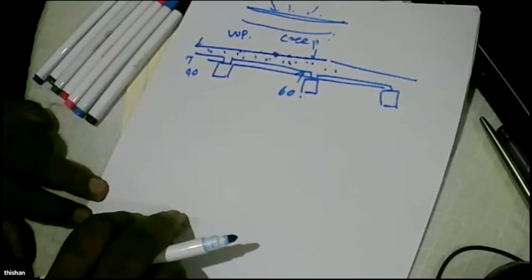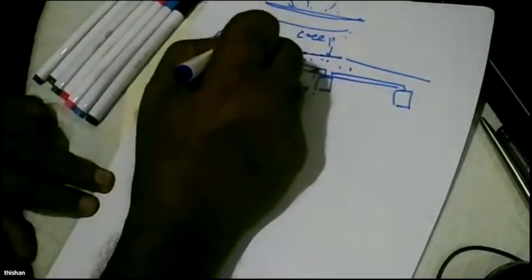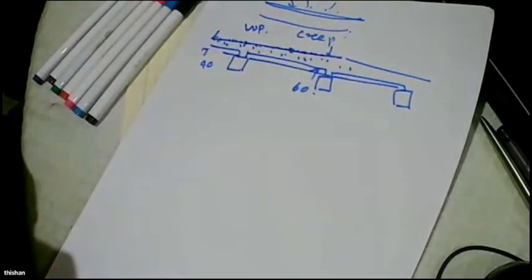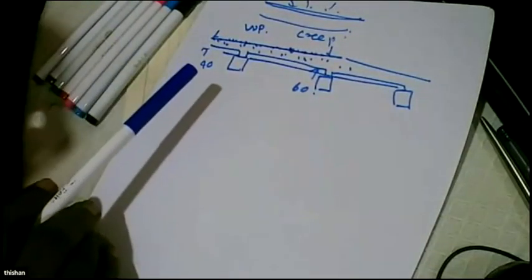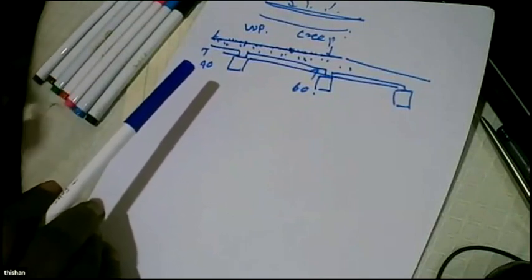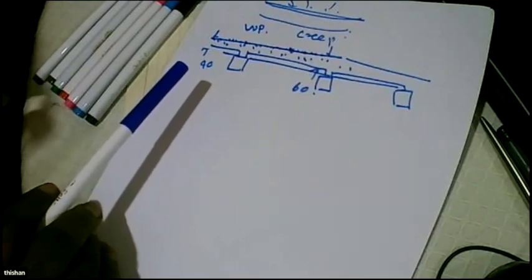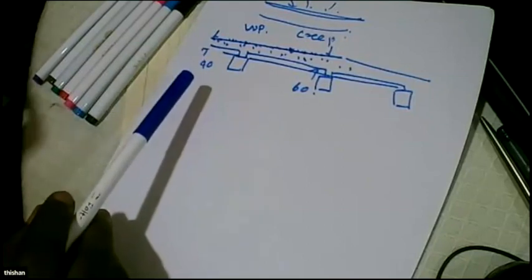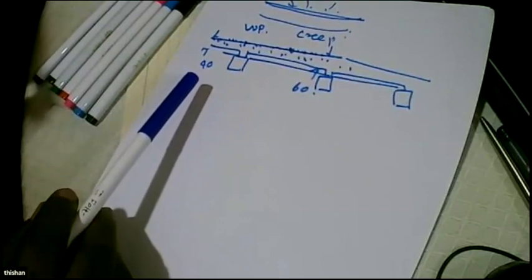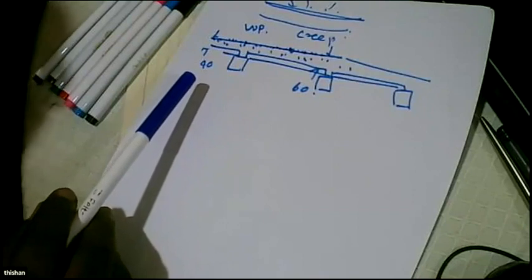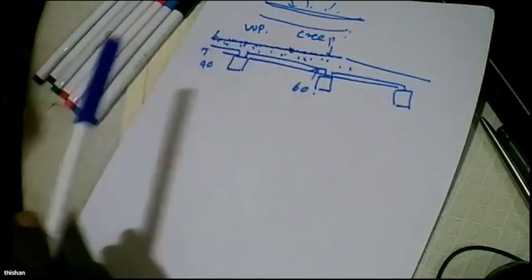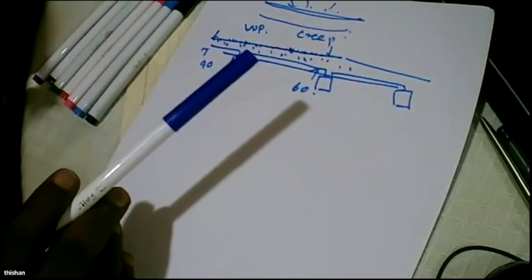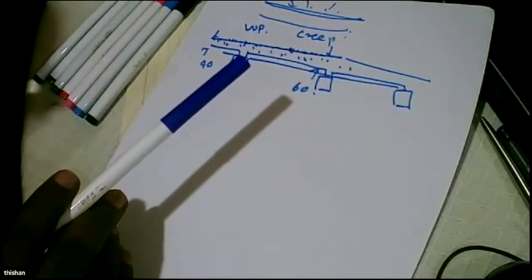So there are so many things you can do. Because the whole idea of embedding chips here is that, rather than having a concrete cement based surface, what is exposed to the rain will be a chip-based surface. And we know chip-based surfaces are much harder and more erosion resistant than concrete-based or cement-based surfaces. So the whole idea is we spread a pre-prepared mix of pebbles, marble pieces, terrazzo chips, you name it. It can be glass chips, anything. That is hard materials. And then use a float and firmly embed those things into the fresh concrete.